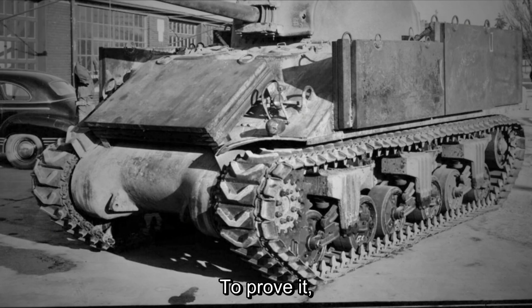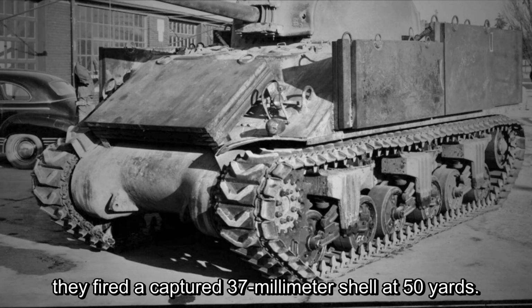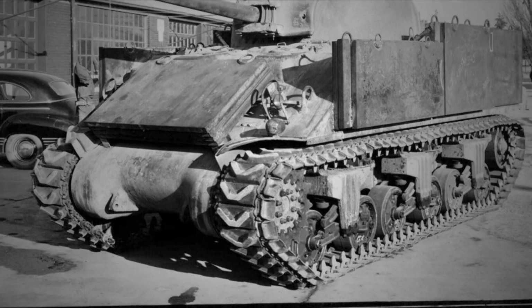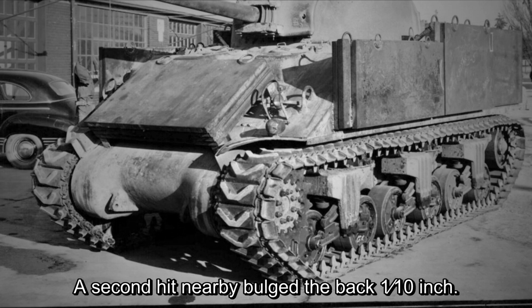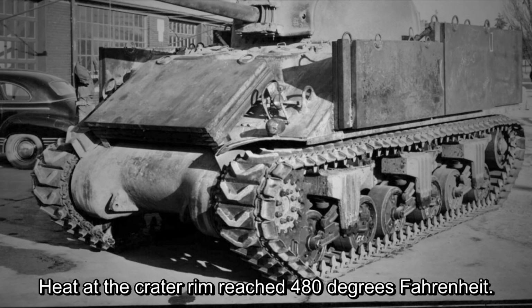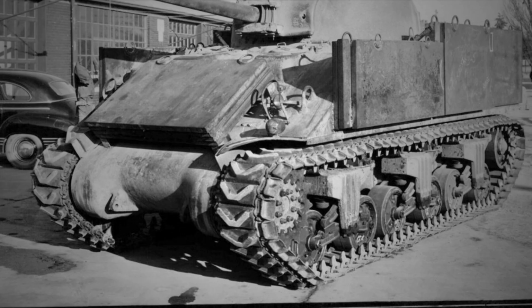To prove it, they fired a captured 37mm shell at 50 yards. The round struck, smoked, and stopped. A second hit nearby bulged the back 1/10 inch. Heat at the crater rim reached 480 degrees Fahrenheit, resin charred but no crack formed.